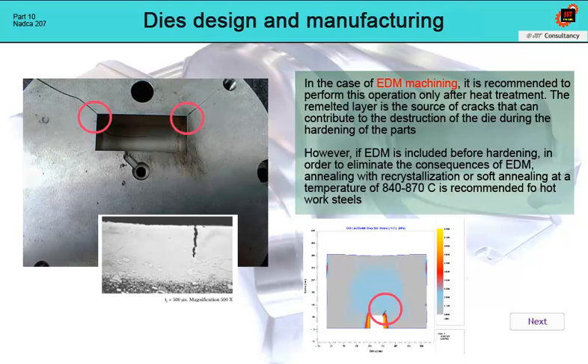In the case shown in the picture, this was not done. Moreover, the shape has sharp corners with 0 radii. Cracks after hardening are the result of the fact that the layer was not removed and annealed before hardening, and that the shape was made finished without radii and necessary additions.